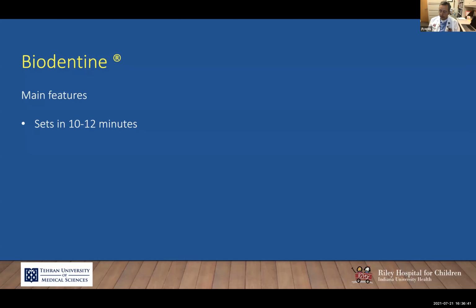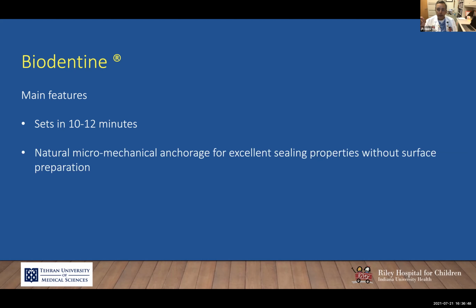Some of the important properties of Biodentin: one, it sets in about 10 to 12 minutes. That's a difference with MTA. MTA takes a long time to set. Also, there is a natural micromechanical anchorage for excellent sealing properties without any surface preparation. So you can place silver diamine, and then over the silver diamine, you can place Biodentin as a liner. You really don't need any previous prep of the tooth because the mechanical properties of Biodentin will give an excellent margin adaptation. One of the reasons that we call Biodentin as well as MTA dentin substitutes is because these two materials have very similar mechanical properties to human dentin.